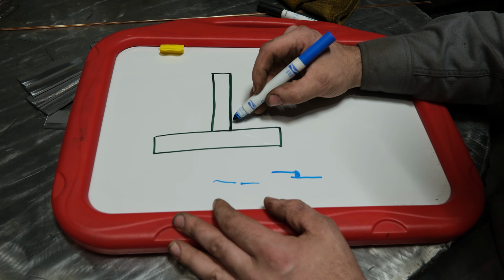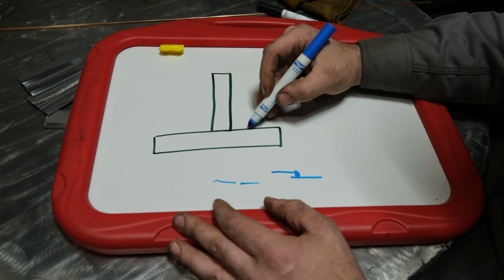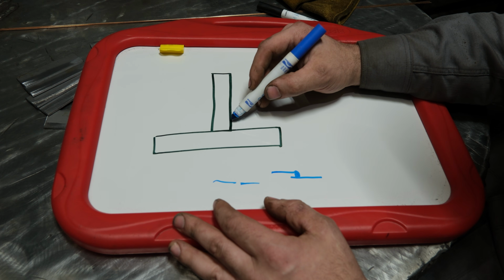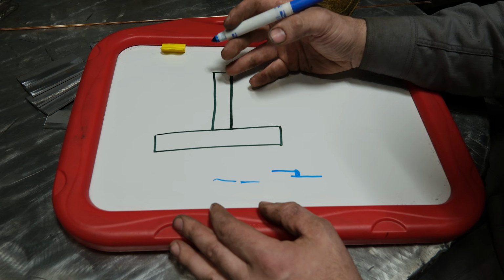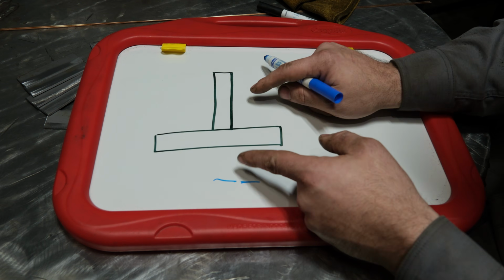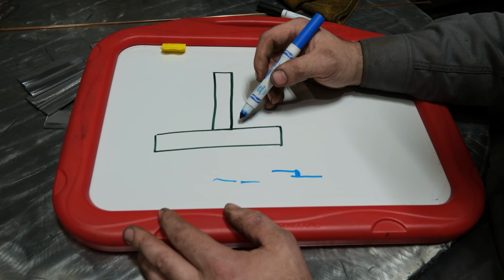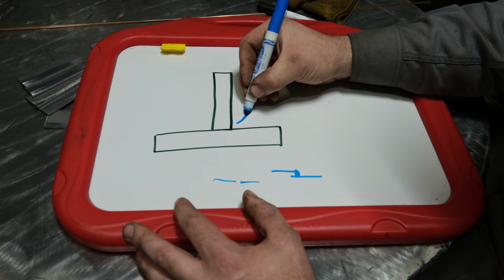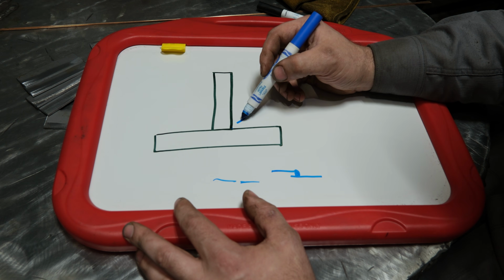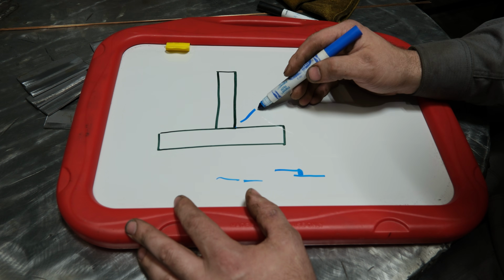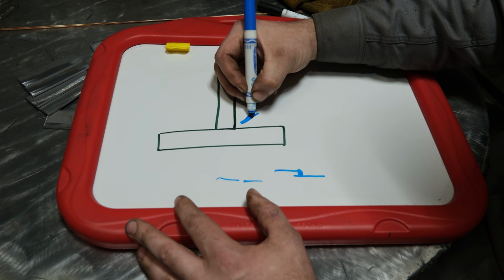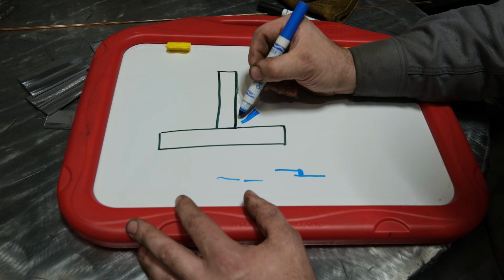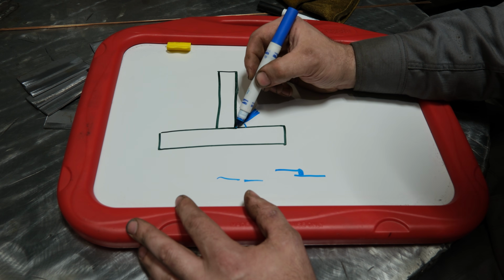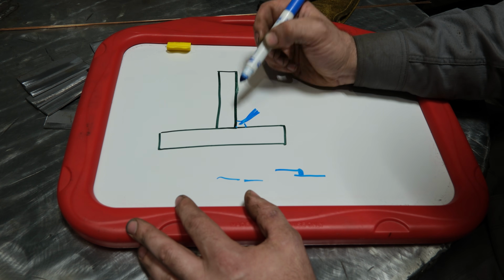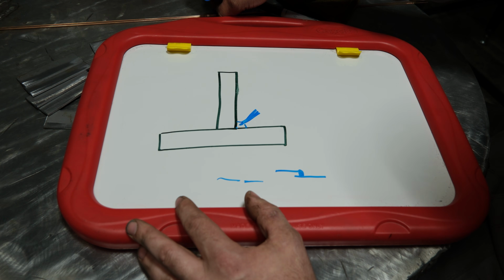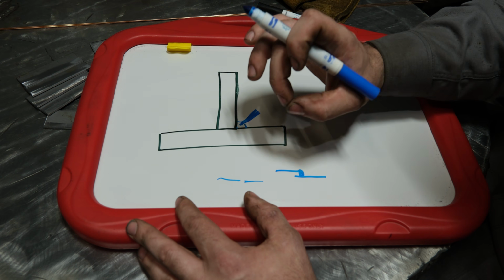And that's because, well, if your arc wanders over to this upright plate or down here instead of directly in the corner, you're going to undercut it where it chews into the steel, and it's going to look bad. Not to mention, you have to have a pretty steady hand to do even a 3 to 4 inch long weld that's perfectly straight right where you want it. So the biggest thing here, you want to focus your tungsten to be right at this corner, and you want the angle to be more or less at 45 degrees. This isn't even 45 degrees. It would be more like this angle right here, to where that arc cone is hitting up to here and to here. And your gap from this inside corner to the tip of the tungsten needs to be about whatever your filler rod is. So about 1.6 millimeter, 1/16 of an inch, maybe ever so slightly more.